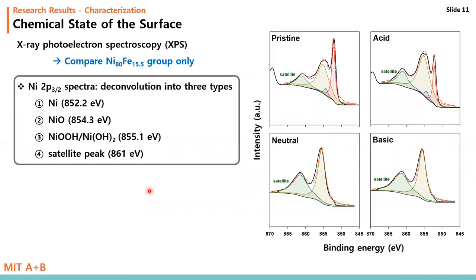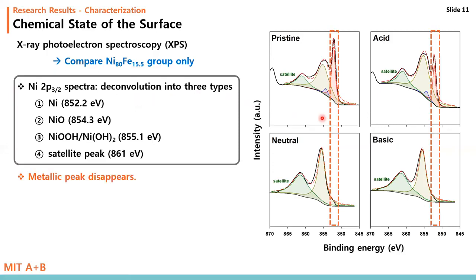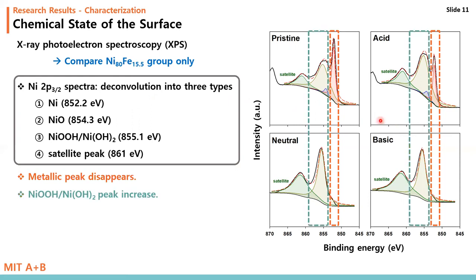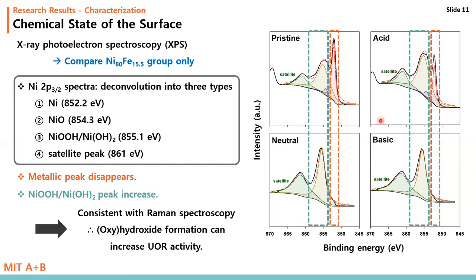To further identify the chemical state of the surface of the treated alloy, X-ray photoelectron spectroscopy analysis was performed. The high-resolution nickel spectrum can be deconvoluted into 3 types assigned to nickel metal, nickel oxide, and nickel hydroxide and oxyhydroxide. Here, the metallic nickel peak of electrodes treated at neutral and basic pH conditions has almost disappeared due to the successful generation of metal hydroxide and oxyhydroxide form. This result is consistent with the observation in the Raman spectrum.